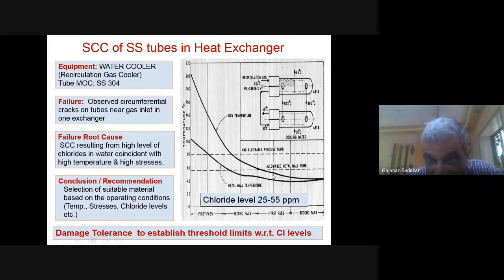Then I plotted these graphs, and I found that the problem is supposed to occur only in this region, that is the first region, because afterwards stress corrosion cracking was not occurring, because metal temperatures were comparatively low and the phenomenon was not occurring. Now imagine somebody found this type of threshold levels at that time based on some studies. I'm sure they used fracture mechanics techniques to do these threshold level studies, along with corrosion and the mixture of the stresses. So this is the case study which explains the damage tolerance, how to establish it using those threshold levels. That's what I studied.